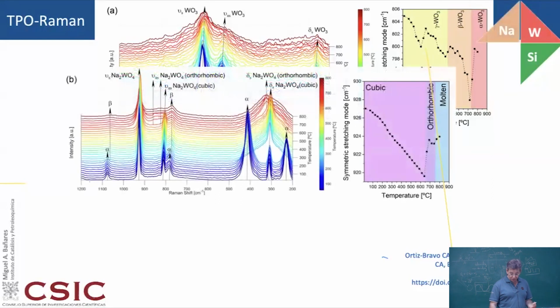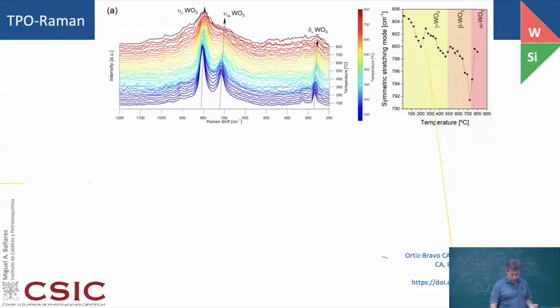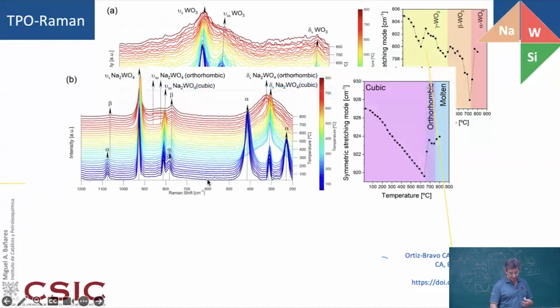Now, if you have sodium, now you don't have only tungsten oxide, which were these bands here, but new bands, which are associated with sodium tungstate. Well, in Spain we say wolframate, because W actually is from wolfram, wolframio, and tungstate is always a weird word to me. And anyhow, the tungstate. So basically, as you increase temperature, what you are observing is that you also see changes. You are going from a cubic tungstate to an orthorhombic one, and then it melts.